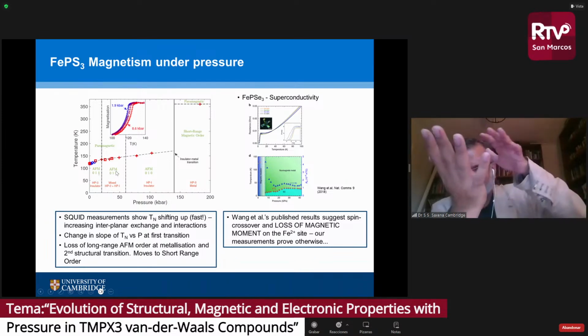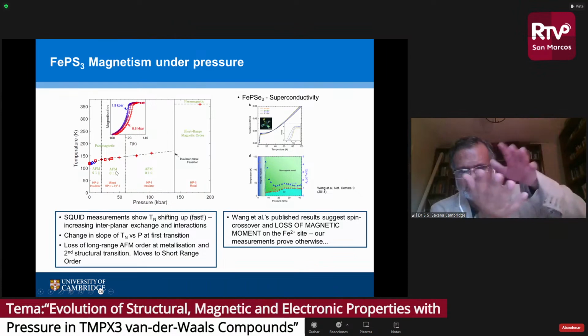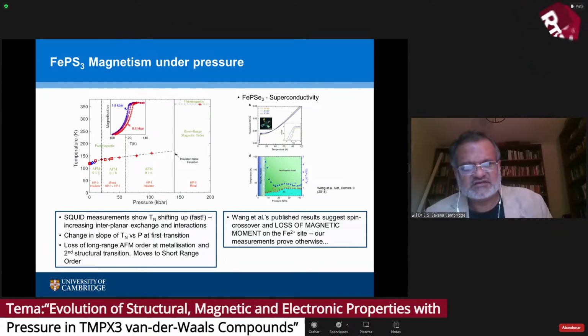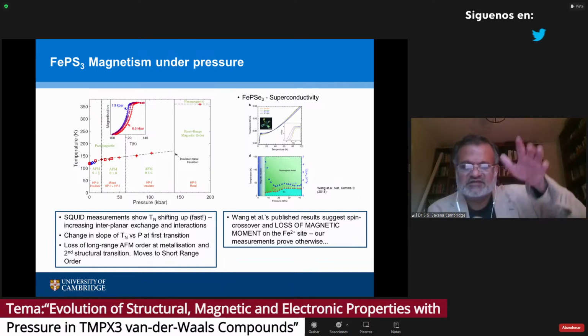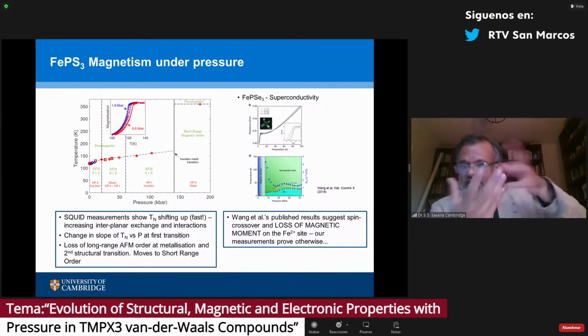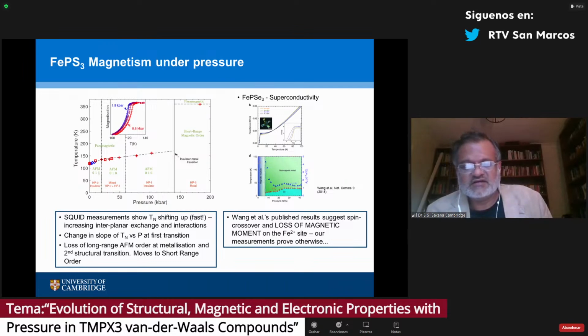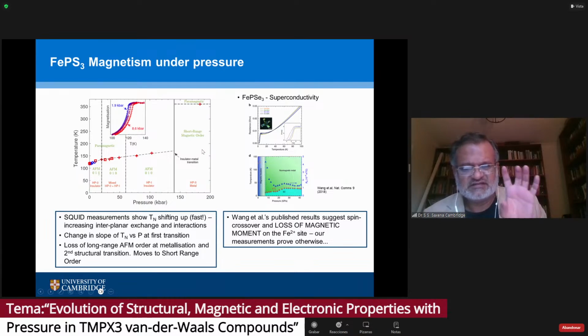As I told you, when the layers slide against each other and reform, you see the first phase area, and then they still remain fully magnetic, but the transition is actually strengthening, goes up a little bit, and then comes the van der Waals collapse, and the system becomes metallic. But also within that, as in the previous slide I showed you, you have short-range magnetic order which emerges in this space.